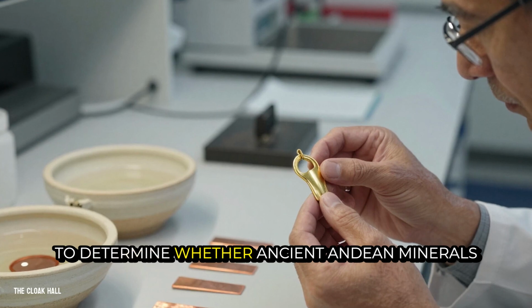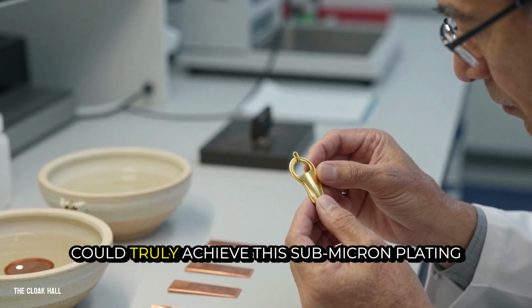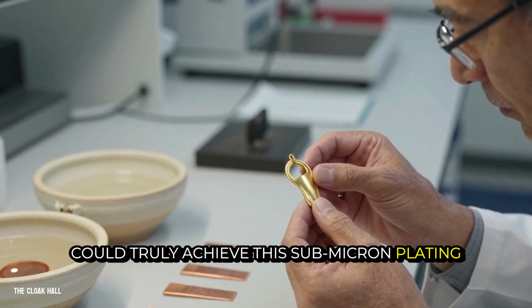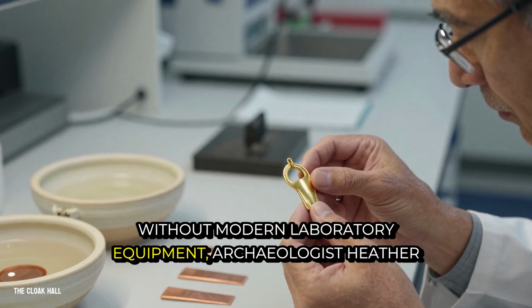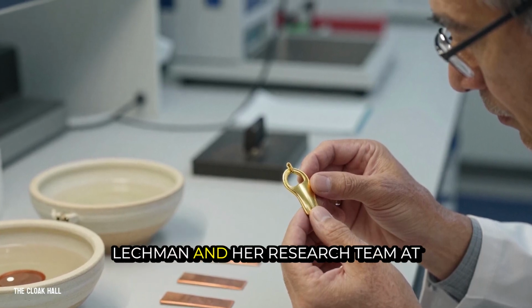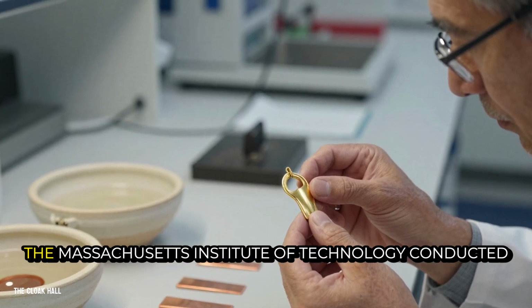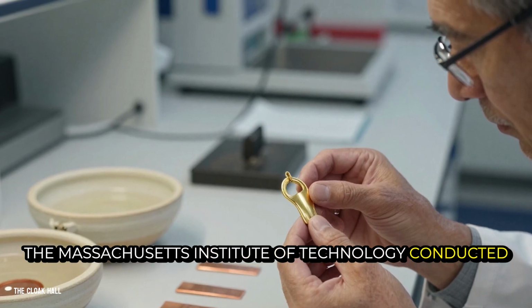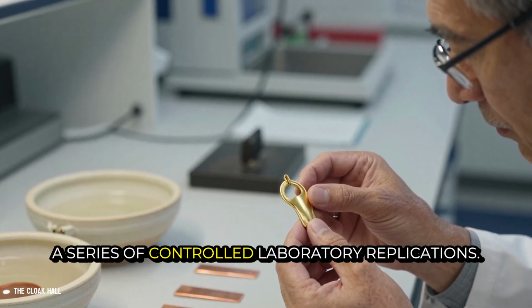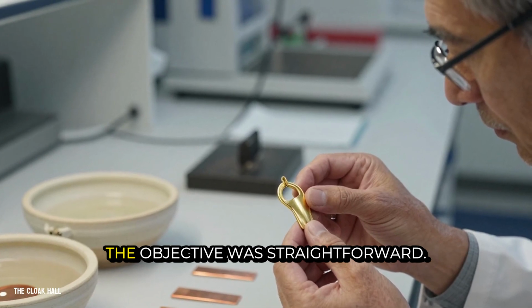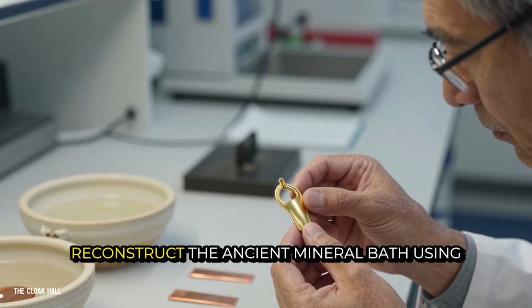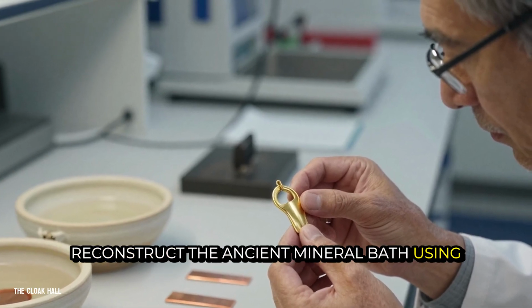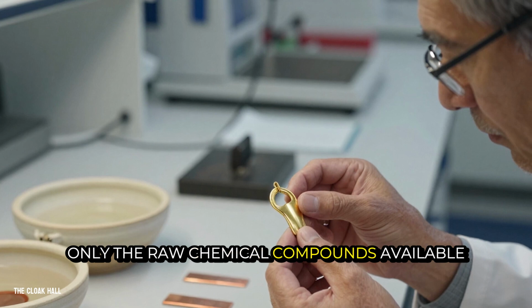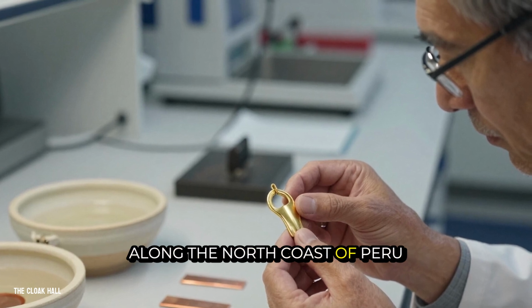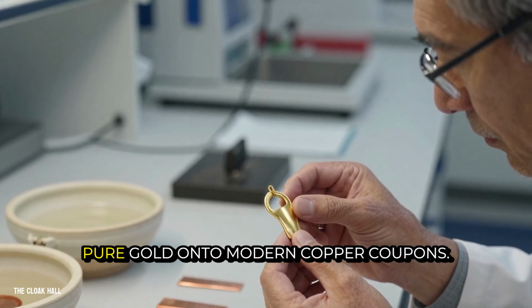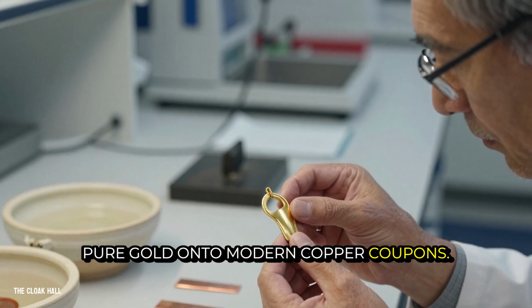To determine whether ancient Andean minerals could truly achieve this sub-micron plating without modern laboratory equipment, archaeometallurgist Heather Lechtman and her research team at the Massachusetts Institute of Technology conducted a series of controlled laboratory replications. The objective was straightforward: reconstruct the ancient mineral bath using only the raw chemical compounds available along the north coast of Peru and test whether it could plate pure gold onto modern copper coupons.